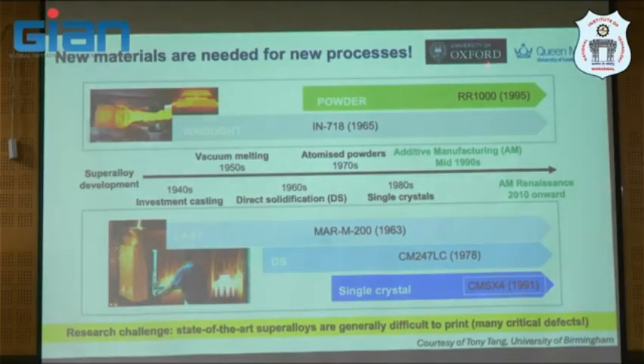And we usually try to refer to CM247 because this is a material introduced in 1978, which is optimized for directional solidification. Directional solidification is used a lot in the aerospace industry because they have a high volume fraction of gamma prime, 65% to a bit above, so 65% in nominal composition. 718 is actually an older material, back in 1965, but this material is very superior in the sense that it is used a lot in the aerospace industry. No one can replace this yet.